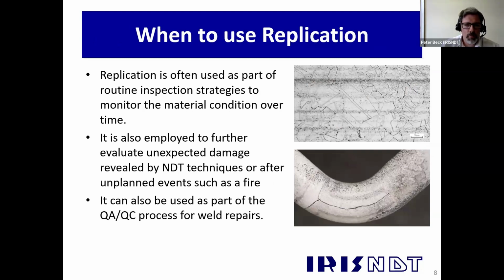I suppose the key thing is to know when to use replication. There are times when it makes more sense to replicate than others. So we typically use this as part of an inspection monitoring system. So as part of an outage on a plant, doesn't have to be a power station, they would generally assess which welds might need replicating. Might not actually just be welds. Sometimes they also look at parent material. So some bends and other components can be subject to degradation. And then as plant gets older, you typically also look at the straight sections of pipe as well.